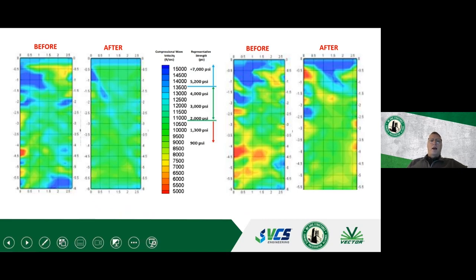You can see how significantly that trunnion block changed, and these photos kind of slice it as you look through the thickness. This is giving you different images because we found voids. That red area inside was actually honeycombing and voids, and the epoxy injection was able to fill all of those. When you start the epoxy injection, in a lot of cases, you don't stop till you get it done, because you want to keep those ports open. I think this was 22 hours of straight injection to achieve these results. The client was thrilled, and the material's been working very well since then.